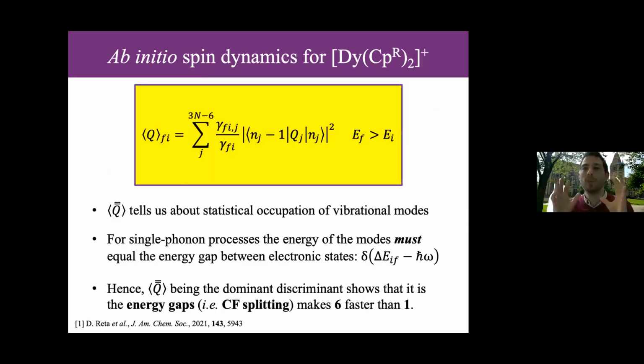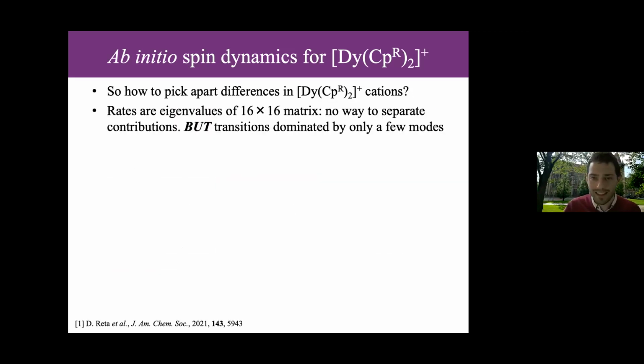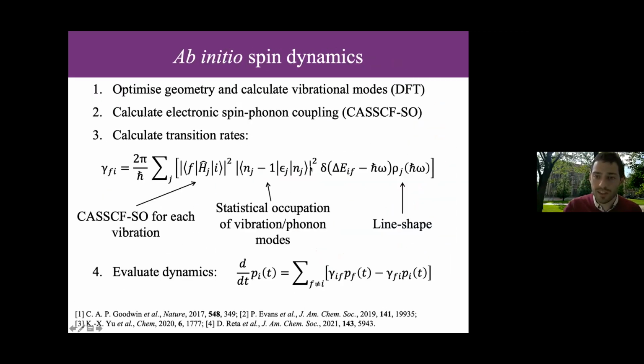So what does that mean? Let's have a look at this term a little bit more closely. So remember, this occupation term is telling us about how the excited vibrational levels of some mode J are occupied at some given temperature. Okay, but recall that because of the delta function, so I'll go back again to that equation just to refresh your memories. Because of this delta function, the actual energy we are using for any relaxation step must be equal to the difference in electronic energies. That is how we define h bar omega being the vibrational energy in this expression.